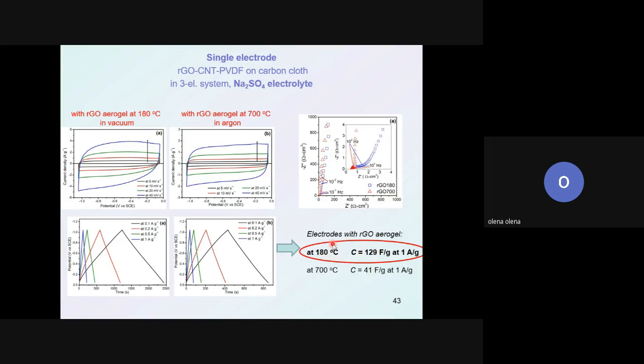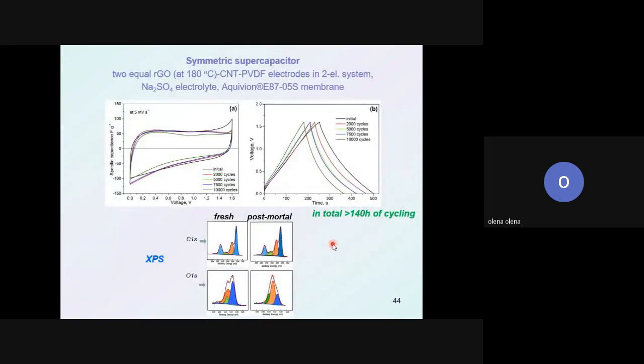And this one we use for preparation of full device, symmetrical capacitors. We use two equal reduced graphene oxide CNT PVDF electrodes with this electrolyte and special membrane. And as you can see, we study cycling. It was 10,000 cycles. We have almost rectangular shape and triangular, almost ideal. For long cycling, in total, it was more than 140 hours.